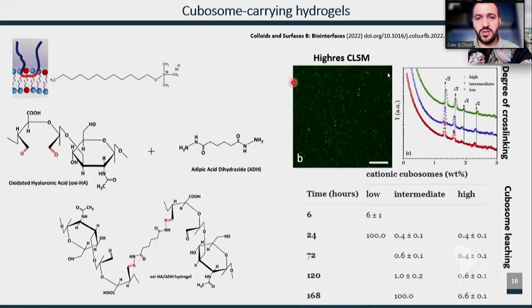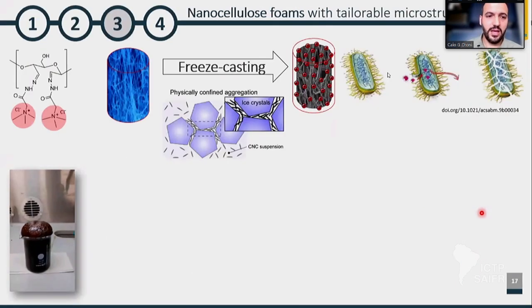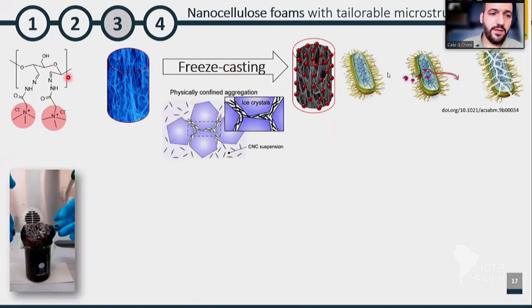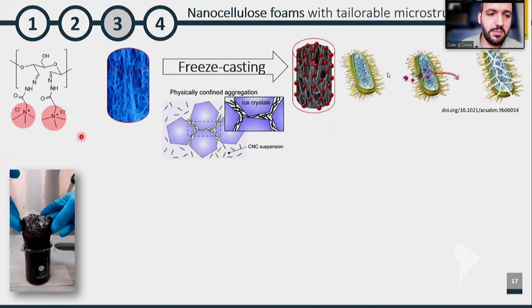And we can still see the incorporation, it's fine, it's well distributed, it's beautiful, but the leaching, you can see here the leaching. When the cationic cubosome content is low, the leaching takes place completely within 24 hours. When we put more cationic cubosomes, it still does, but it takes much more time. And for high cationic cubosome content, then it barely leaches. So it takes much longer to this drawback.